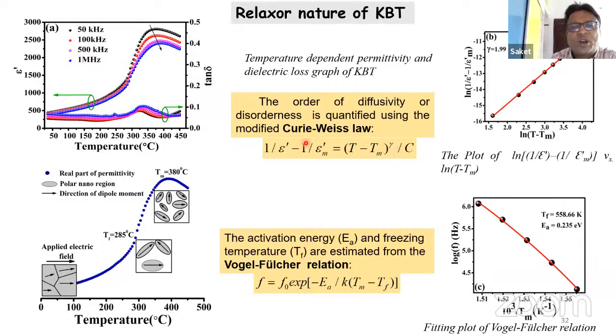Gamma has been used; it is called the modified Curie-Weiss law. When gamma is equal to 1, then it is the standard Curie-Weiss law. It is a normal ferroelectric, not a relaxor ferroelectric. But if gamma varies between 1 and 2, then it gives some signature of a relaxor, this frequency dispersion. If gamma is close to 2, then it is a perfect relaxor. In the case of KBT, it is 1.99. It is a good relaxor.